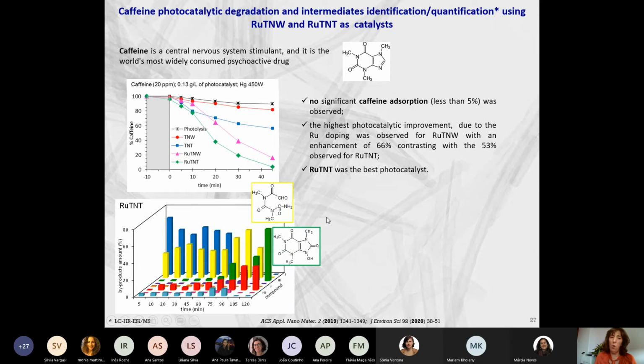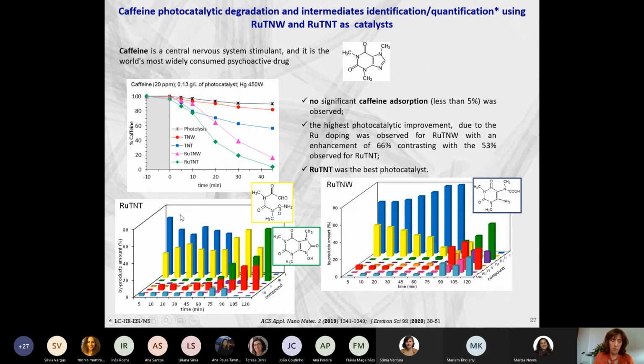But what we know is when we compare the intermediate products that are forming during the irradiation, that is also a very important parameter if you want to study the toxicity of our proposal, okay? And if we compare these two time profiles, we can see that, in fact, using ruthenium nanotubes or ruthenium titanate nanowires is not the same in terms of formation of byproducts. So this is telling us that probably we have different mechanism of degradation of the caffeine in this case.